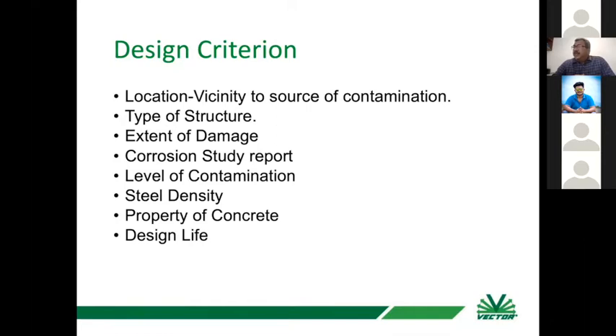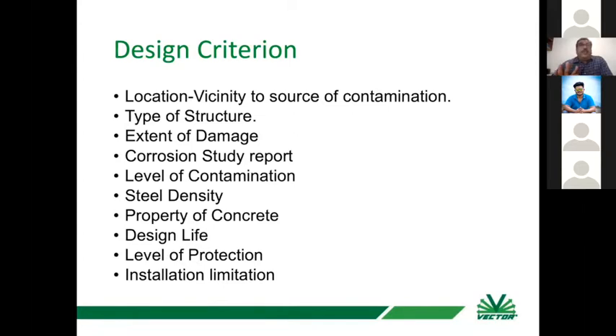Design life. This is the design life of the anode, like the anode should function for 20 years, 25 years, so you can have a corrosion-free life of the structure for 25 years. That is what I'm emphasizing. I've been doing repairs and rehabilitation for 25 years, almost 26 years, and I found that 75% of the structures have failures or distress mainly due to corrosion. If you can delay the corrosion for a long time, you can have fewer failures and good structures. So the design life of the anode is to be considered, along with the level of protection, which I explained earlier. Installation limitation: if access is not there, or if other non-structural changes need to be done to install the anodes, then it comes into the design criteria.